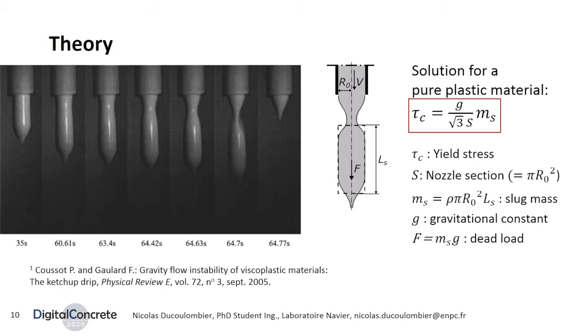Indeed, the same discontinuous flow was previously identified in this context and studied by Coussot and Gaulard, who provide a theoretical frame for Herschel-Bulkley viscoplastic fluids. It was shown that the slug mass is mainly controlled by yield stress and eventually by viscosity for high values of extrusion speed V, whilst surface tension effects can be neglected. From this analysis, we then compute the straightforward solution for a pure plastic von Mises material with a yield stress tau c.